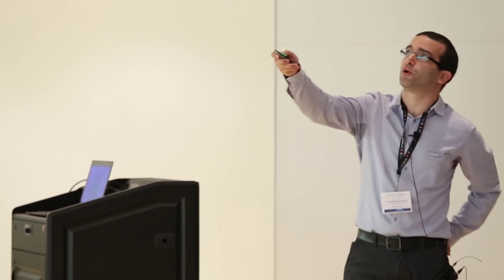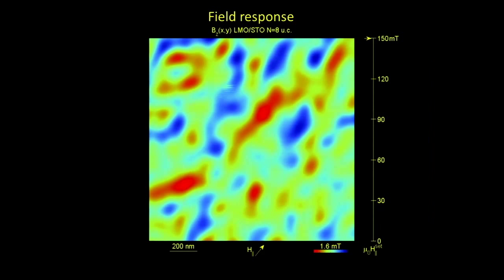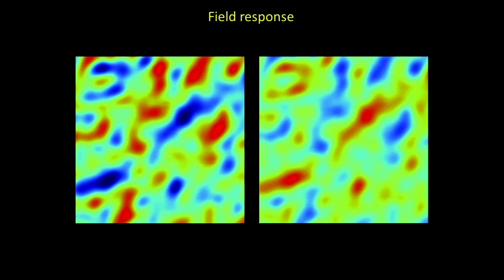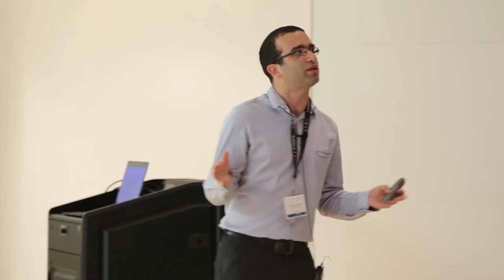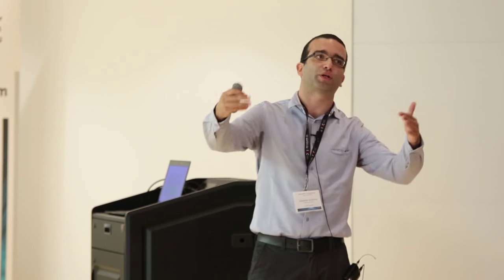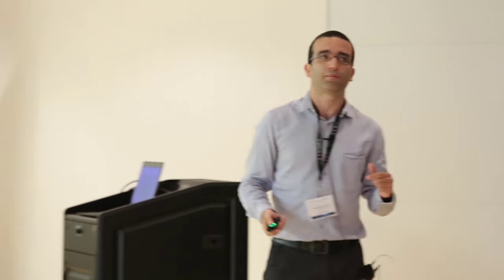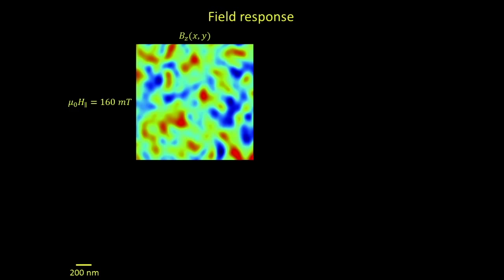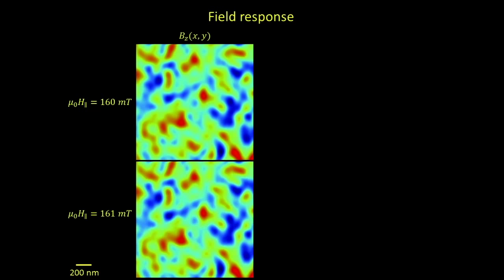Another interesting feature: the last frame and the first frame have colors reverted with respect to each other, which greatly differs from a classical ferromagnet where you would have domain wall motion — there's no reason why reversing the magnetization should produce a reversed image. Looking more carefully at the changes: for an 8-unit-cell sample at 160 milli-tesla versus 161 milli-tesla, the images seem almost identical — but subtracting them reveals four to six distinct magnetization reversals of the in-plane magnetization.